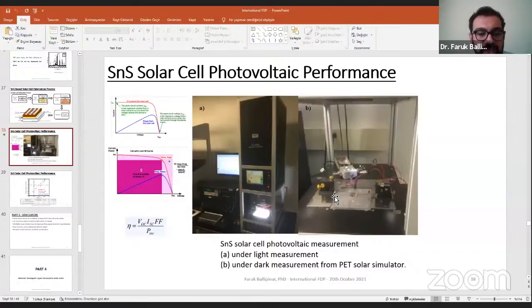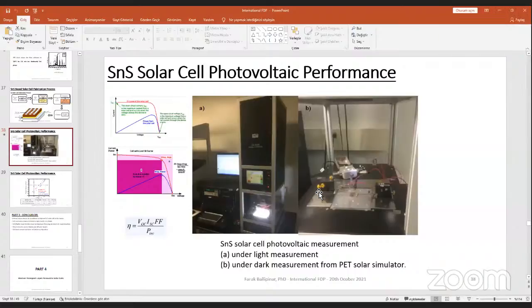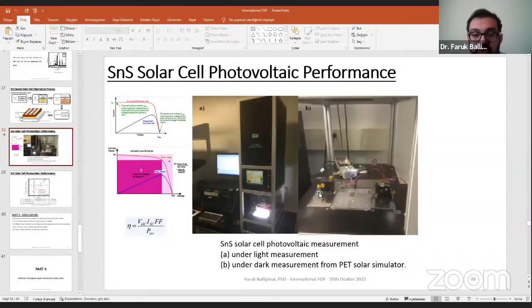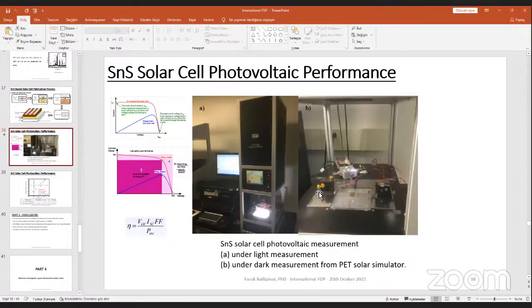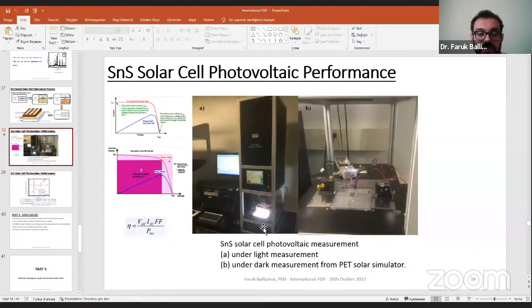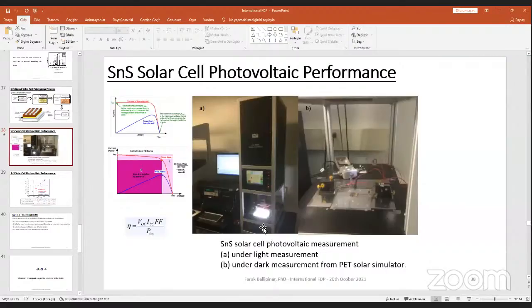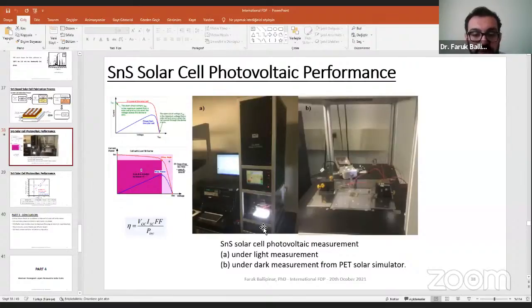So this measurement can be done in the air because we are measuring inorganic type. It's not that sensitive to oxygen. I guess the question is related to oxygen in the air during the measurement. For the OPV, perovskite, or dye-sensitized, these are air sensitive solar cells. This solar simulator is in the glove box under nitrogen atmosphere. So there was no particular issue if we measured our solar cell in the glove box in the nitrogen atmosphere. So there is no oxygen problem during the measurement. But for inorganic type, it's not a big problem. So we can basically use the setup in the air.